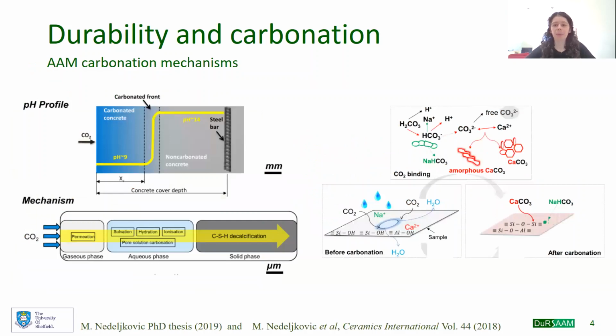The carbonation is happening in 3 steps. The first step is the diffusion of the CO2 in the materials. The second step is the dissolution of the materials within the pore structure. And the third step is the carbonation of the main phases. And for alkali-activated materials, it's the decalcification of the C-S-H phases and N-A-S-H phases, so of the gel phases.